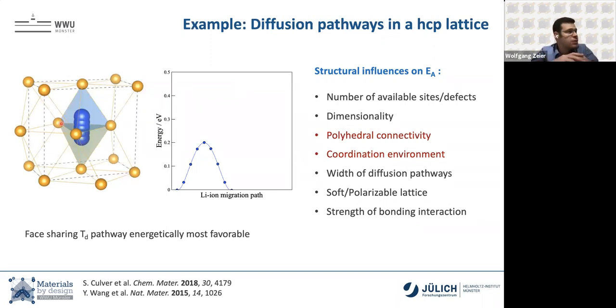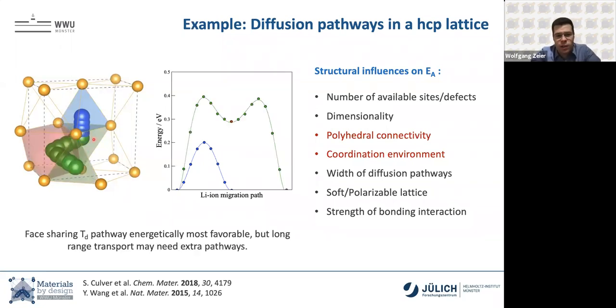And so if you think of this in terms of a chemical reaction, there's no change of the reaction coordinate. But if you think of it like this, then you change your coordination from 4 to 3 to 4. That's cleaving one bond, that's forming a new one, that doesn't cost a lot of energy. But for long range transport in the structure, you would then have to jump via an octahedral site. So the coordination changes from 4 to 3 to 6. That costs a lot more energy. And then the lithium is, in this case, unhappy to sit on an octahedral site. So if we overcome the barrier, it's more likely to just jump backwards. So a lattice like this with a lot of octahedra and tetrahedra is usually not a good ion conductor. So the polyhedral connectivity matters, and the change of the coordination environment.